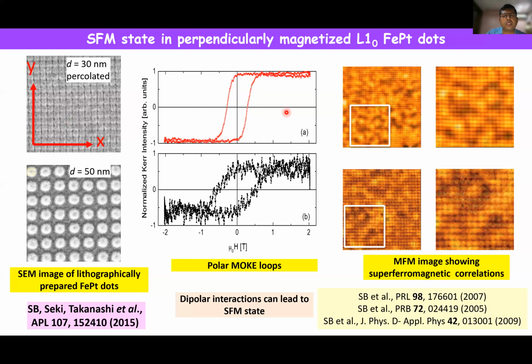And you see a beautiful hysteresis loop. You see these ferromagnetic domains where many particles switch together. However, in this system, the dot array is absolutely isolated. There is no exchange interaction, just dipolar interaction, but you still see this hysteresis loop.